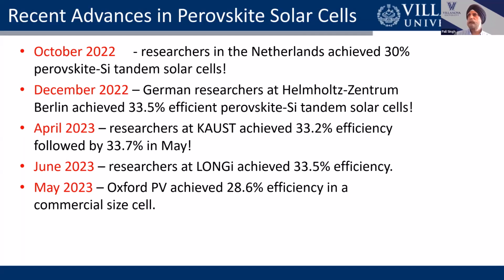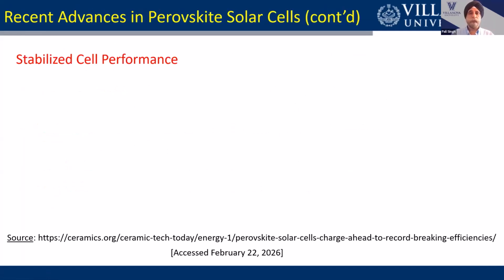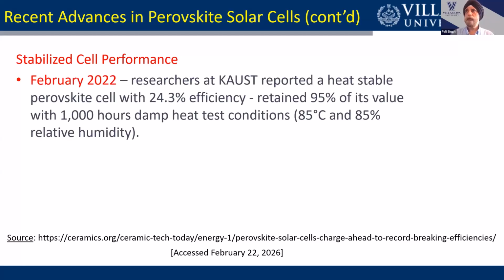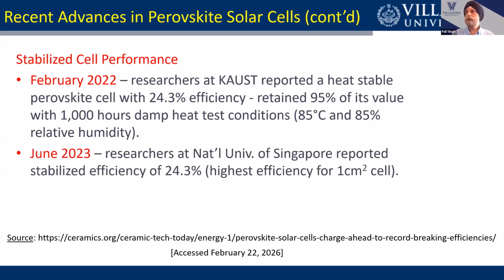So you can see that the technology has been evolving very rapidly in terms of cell efficiency. Looking at what is the stabilized performance, we can see in February 2022, researchers at KAUST reported a thermally stable perovskite cell with 24.3% efficiency. So it retained 95% of its value with 1,000 hours of damp heat test conditions, so 85 degrees C and 85% relative humidity. In June of 2023, researchers at the National University of Singapore reported stabilized efficiency of 24.3%, which is the highest efficiency for a 1 square centimeter cell in terms of stabilized cell performance.